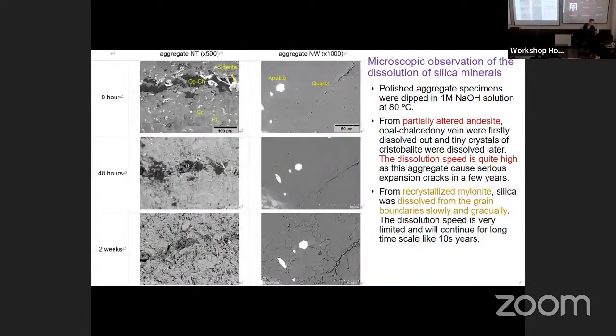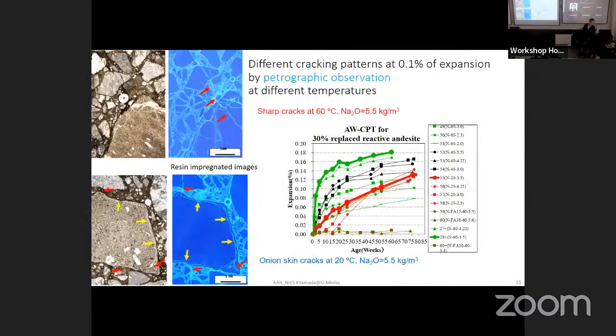This is a hypothesis, but if we think so, at higher temperature or with more alkali, too fast a reaction of silica results in a continuous movement of alkali gel outside of aggregate without expansion. This is my hypothesis. So it is very difficult to accelerate ASR expansion, because the alkali-silica reaction we can accelerate. This is a chemical reaction. Higher temperature and higher pH, higher reaction speed.